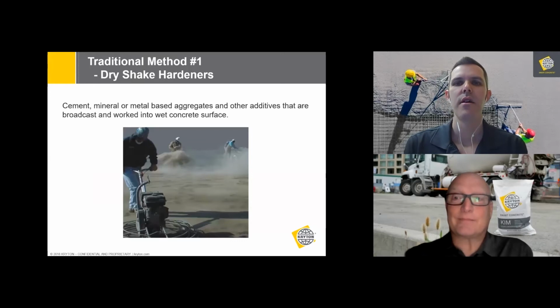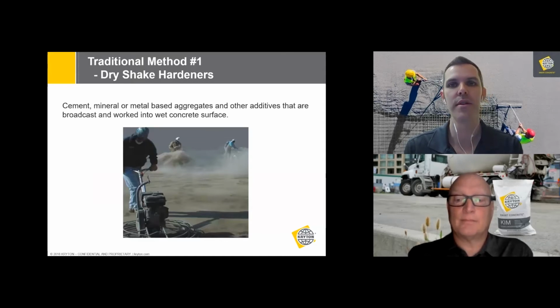Absolutely. John, I think one of the first areas where people will turn to when they're trying to specify a more abrasion-resistant concrete is to use something called a dry shake hardener or a broadcast hardener. Now, these products consist of cement, some sort of additives, maybe finishing aids, and then a wear-resistant particle, often a metallic aggregate or aluminum oxide, which is emery, a very hard-wearing aggregate. And these products get broadcast over the fresh concrete shortly after it's been placed, and then troweled into the surface during final finishing.